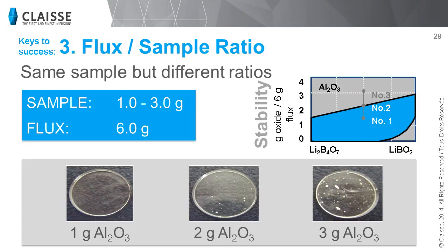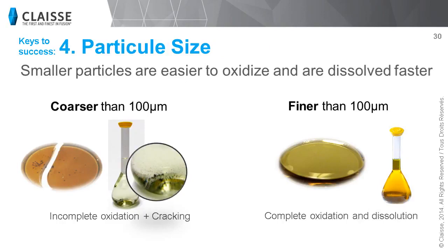As we can see in this example, the particle size of the sample also has an impact on its solubility into the flux. By keeping all the other factors identical, like the flux type, flux to sample ratio, the fusion temperature, and all the others, we can see here that for the same sample, just by decreasing the particle size, we have been able to obtain a homogeneous glass disk without undissolved particles.